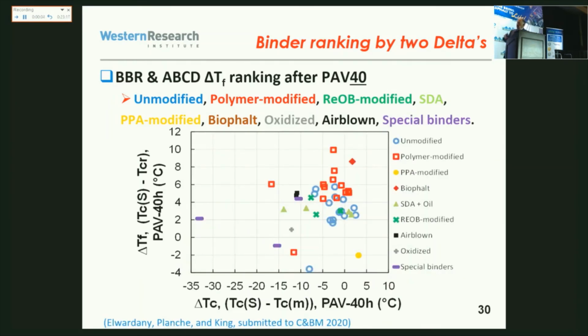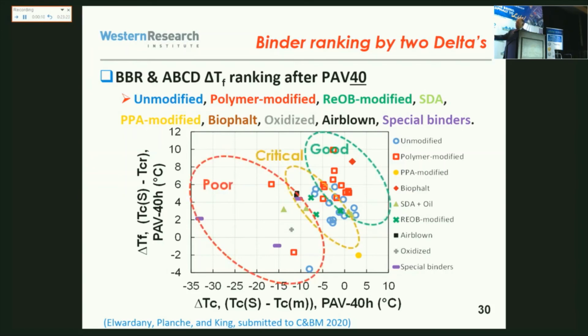Then we say, okay, let's plot delta TF versus delta TC. And so this is what we found. And then I told you that we have field data for half of them. And we are able to see that all the best performers were in this area, the poor performers were here, and then there are some critical binders. And those are the ones which are important.